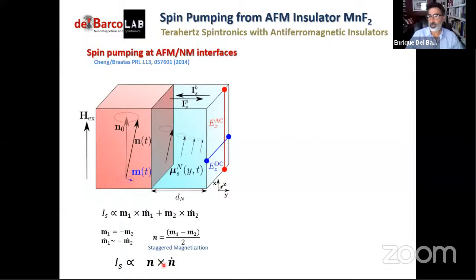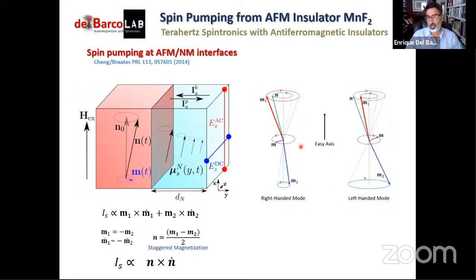But with this description a little more formal than in my previous slide, in which one sublattice magnetization will precess with a larger cone than the other, and then for the right-handed mode and for the left-handed mode, it will just happen the opposite thing. And if this is the C axis and the magnetic field is applied in this direction, well, this mode will be lower, more stable in energy, and this will be less stable in energy. But another thing that you can realize here is that because of this different precession cone angle between these two sublattice magnetizations, you will also have